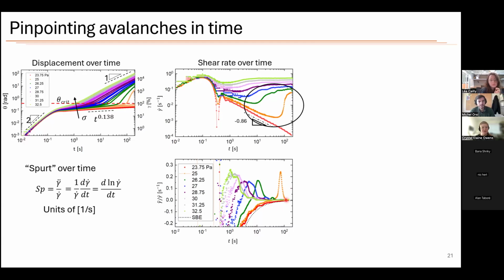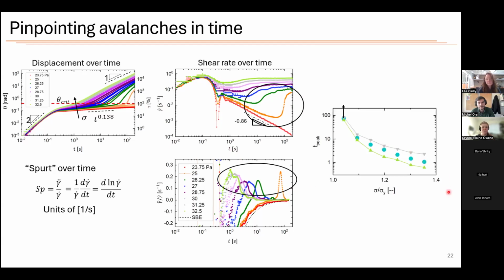And you can see, interestingly, that it shows it clearly for ones that we can see have an inflection point on the other plots, but it even pulls out peaks for the curves that seem like they're just undergoing fairly standard transitions to flow. And so we can take this information and plot the central time of the peak of the avalanche for each of these as a function of the yield stress.